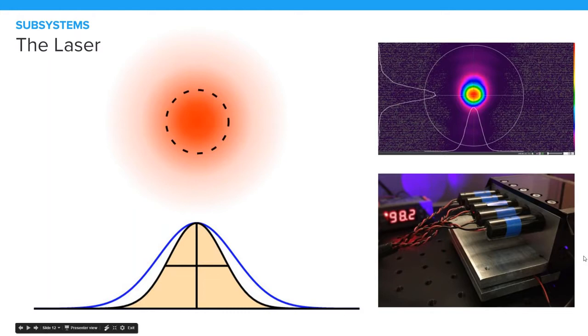So on the topic of laser power and wavelength, you can see the testing equipment that we actually use to make sure the Form2 laser would stand up to the abuse of industry on the bottom right. To simulate thousands of hours of printing, we run the lasers at a higher than normal temperature for hours or days and record the laser spot, which is what you can see above it. So we use specially designed cameras and sensors to analyze and record that laser spot to ensure the beam satisfies size, shape, and power metrics.